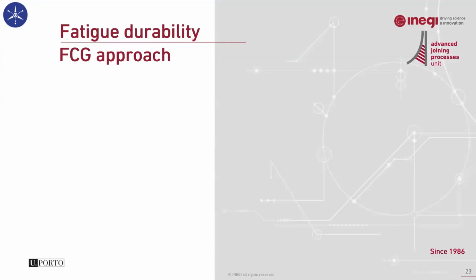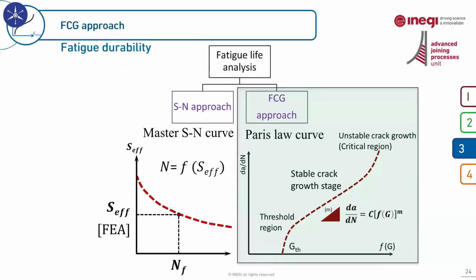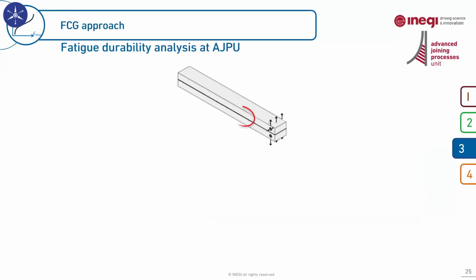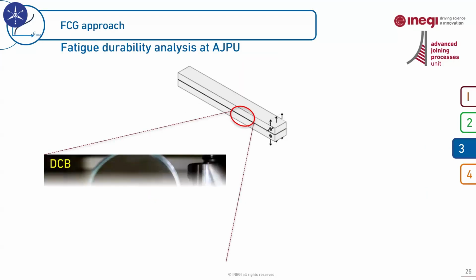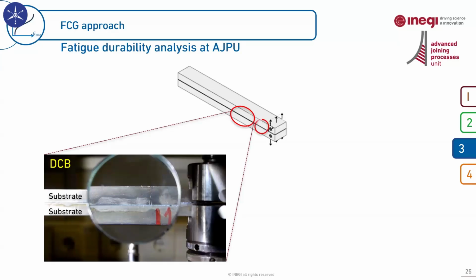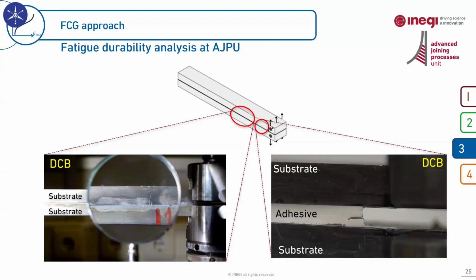Now I'm going to talk about fatigue crack growth. As mentioned before, analyzing fatigue crack growth in adhesive joints is more complex than working with the SN method. Here, I'm going to show you some results and share some findings and insights. Here I show 2 examples of DCB joints tested under pure mode 1 fatigue loading conditions, and several phenomena are visible here in the adhesive layer.